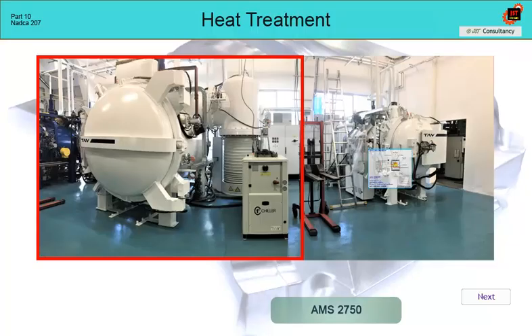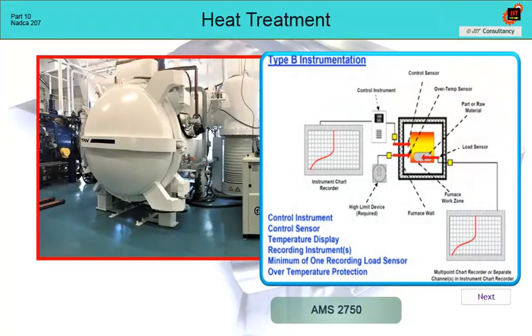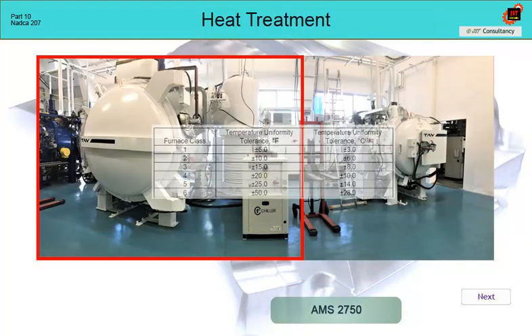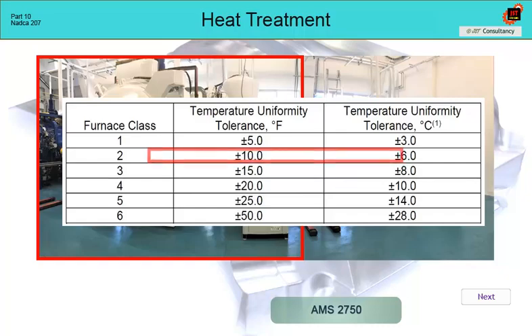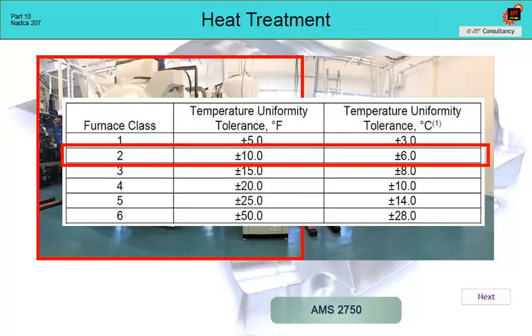Furnace instrumentation should be Type B. Although NADCA 207 does not say anything about detailed parameters, it is required that the temperature uniformity of the furnace be Class 2, ±6 degrees Celsius. The entire temperature control chain must be in a calibrated state according to this standard. This means that TUS, Temperature Uniformity Survey, and SAT, System Accuracy Test, are valid on the furnace.